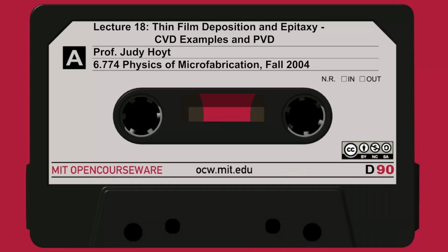Well, a lot of those hydrogens get ripped off during the plasma process, and you're growing so fast they can get buried in the film. So hydrogen incorporation, just by sort of stuffing it in the film, is kind of common in any low temperature plasma process. Also, the temperature's low enough, hydrogen gets in the film and it just sticks. It doesn't evolve. At higher temperatures like LPCVD, the sticking coefficient of hydrogen on the surface is very low, so you don't get so much hydrogen.